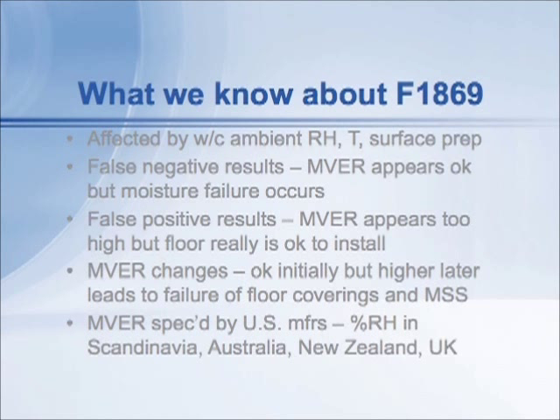We also know that moisture vapor emission levels tend to change. You might measure a floor today and then put flooring down, and if you have a failure, many times we've seen that you come back and repeat the test and you get a higher value later on. That's because moisture within the floor has come up near the surface. So it's a test that changes depending on how the moisture picture within the slab changes. Any test that gives different results depending on the weather, the temperature, and the particular day you do the test is fundamentally going to give you not very useful information.